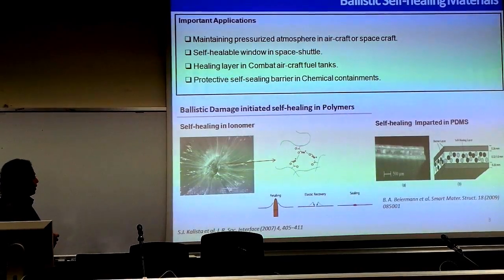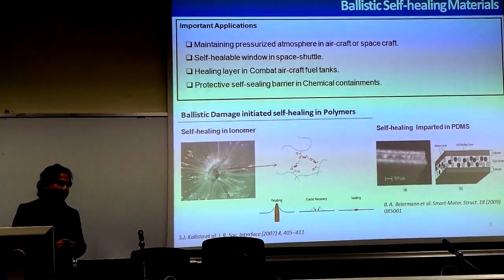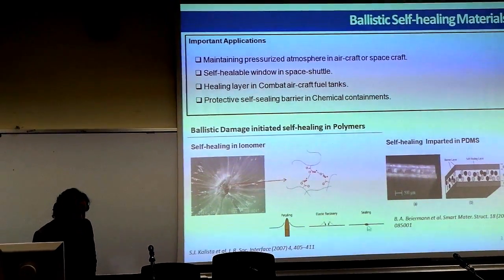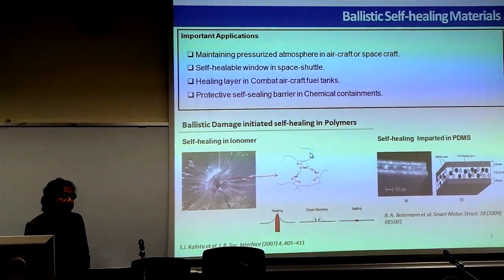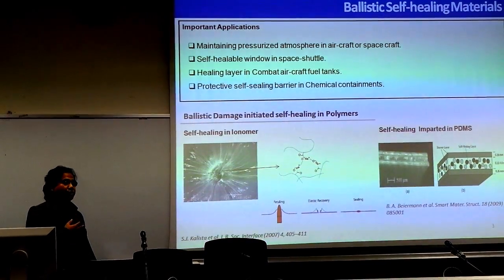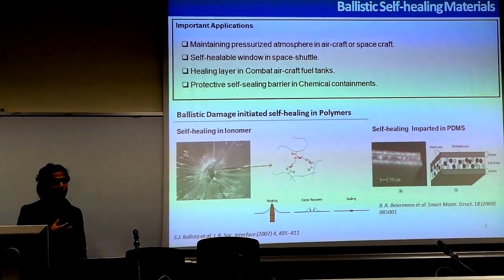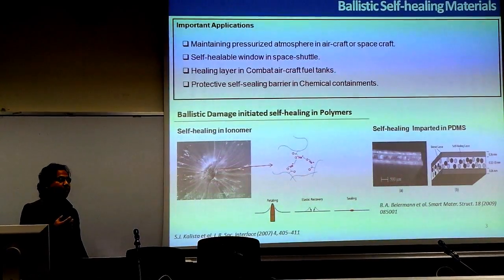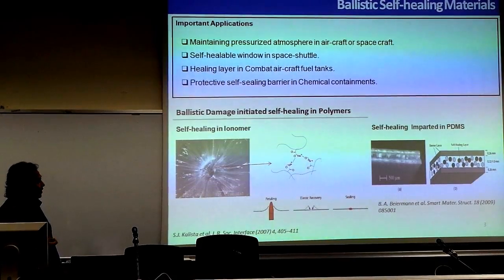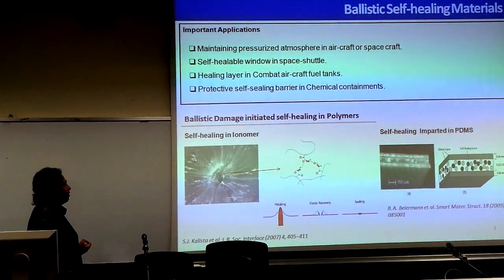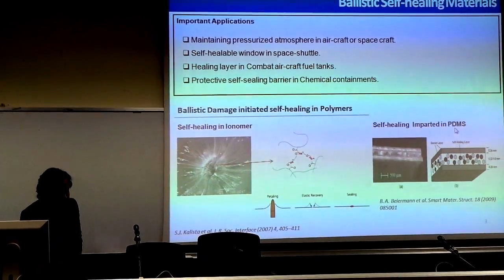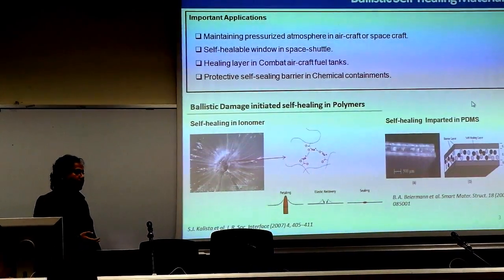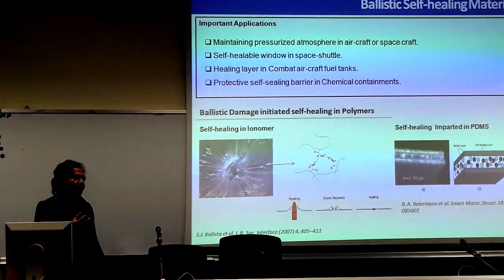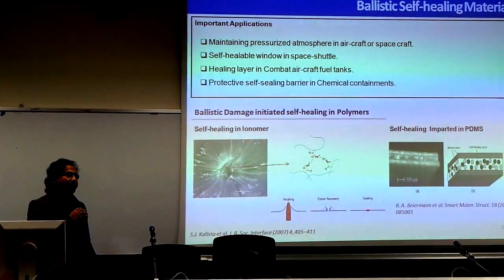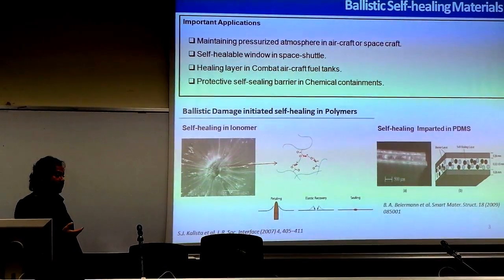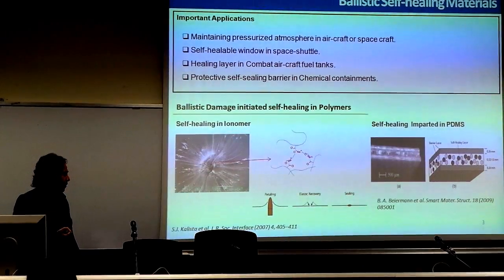The first research work on ballistic damage-initiated self-healing in polymer was reported by Stephen Kalista in 2007. He studied the self-healing behavior in ionomer, and he proposed that the self-healing in ionomer is a function of melt elastic recovery at the impact zone, and a complete interdiffusion phenomenon at the impact zone leads to the complete self-healing of the sample. After that, there has been very little work to develop such self-healing material. For example, some efforts have been devoted to develop a self-healing material based on polydimethyl siloxane, where two different types of microcapsules containing healing agents were embedded inside the laminates of polydimethyl siloxane, and this kind of material exhibited self-healing behavior at very low energy impact damage.